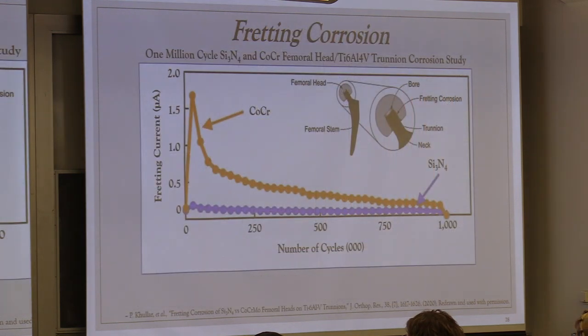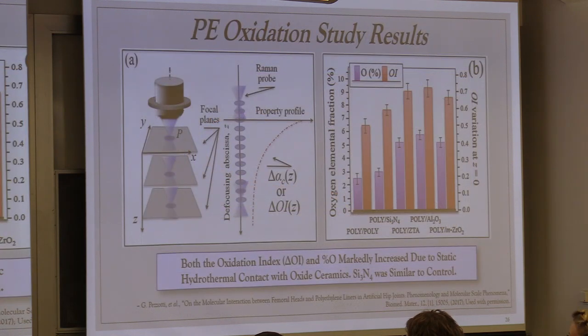Yeah, before I go there, so what's the mechanism here? The mechanism is that actually slight dissolution of the aluminum or the oxide surface actually contributes to oxygen pollution into the tribolayer, whereas silicon nitride, its reaction actually acts as a getter of oxygen. So it has this protective effect. So this is all just short-term data. Hopefully it'll yield a long-term proxy to improve performance and longevity of these devices.